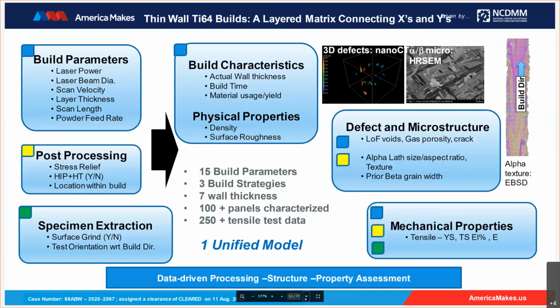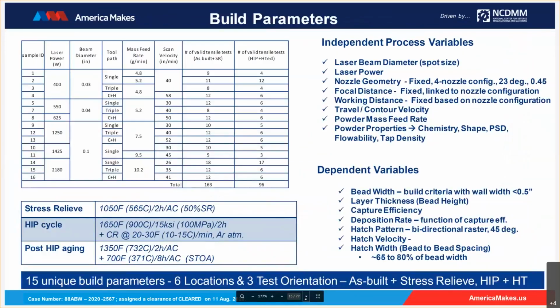So in total, we had 250 plus tensile testing done for this particular build feature, thin wall build feature itself. 100 plus panels looked at. We made sure that the build scope is wide enough, where we cast a wider net out, and the entire goal was to have a unified model which is data driven from processing to structure and then structure to property assessment. To drive down this further in terms of how we are going to look at this, Shikhar is going to take over from here. Shikhar.